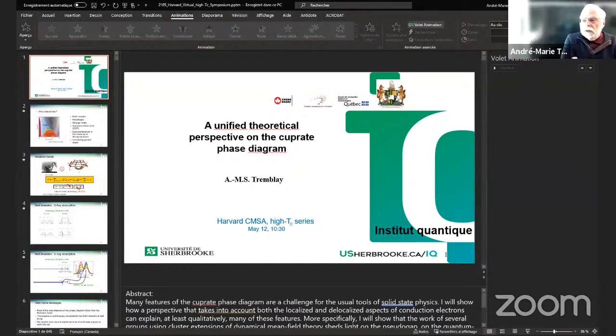Yes. Well, one thing I can say is that if you look at the color plots that I had, you see that the maximum in Tc is in the region where the scattering rate is, I mean, the color here is about the scattering rate. That's the imaginary part of the self-energy. And you see that the maximum occurs where the imaginary part of the self-energy is largest. So that partly answers your question.